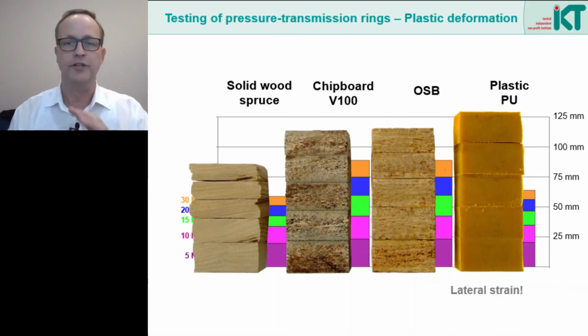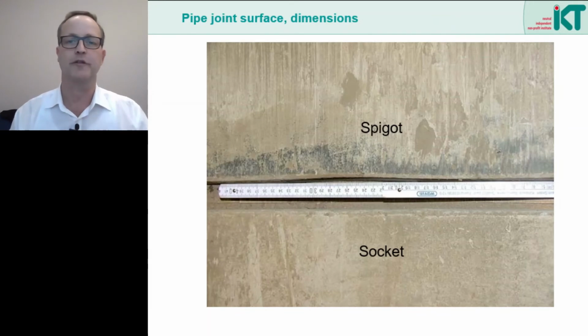If we want to reduce the risk of splitting tensile forces, we have to place a sheet metal between the plastic and the concrete so that the concrete is not torn apart. This is a picture from a concrete pipe string. Here we can see how important it is that the pressure transmission ring can adapt itself elastically or plastically well to the pipe joint geometry.